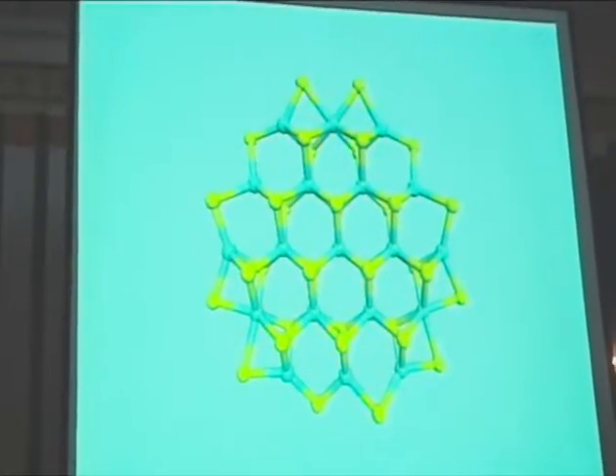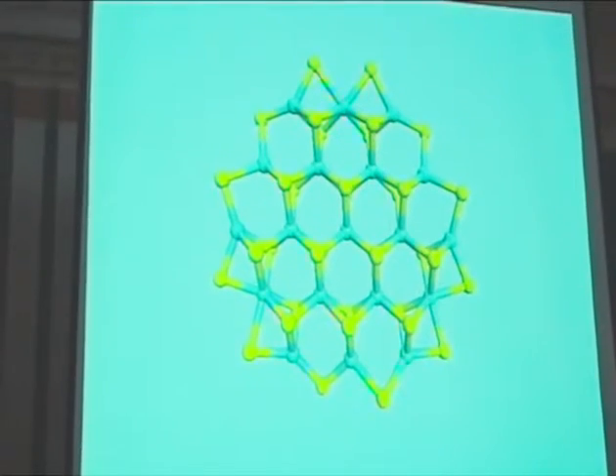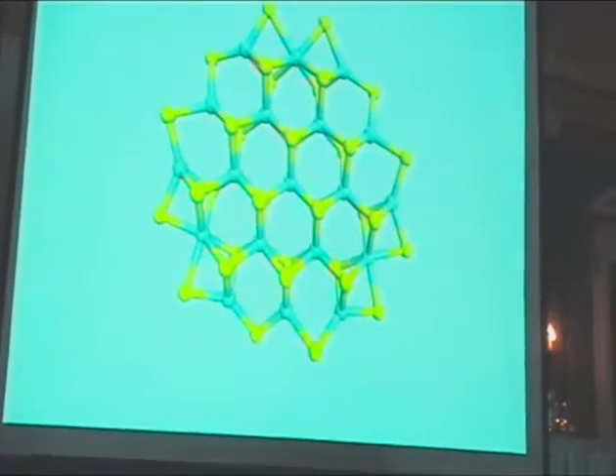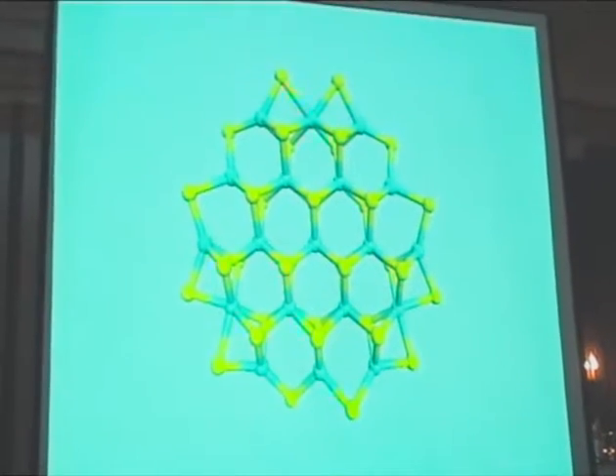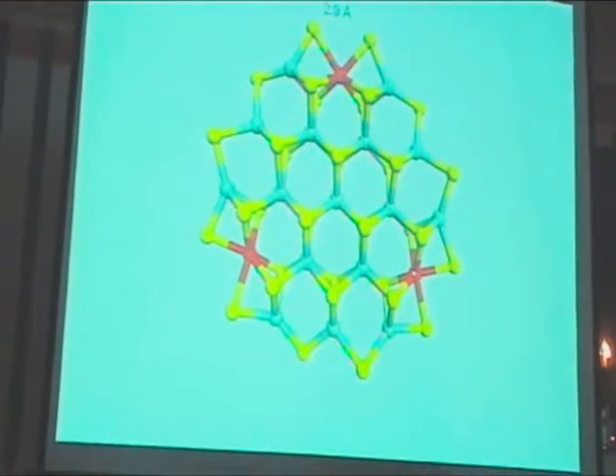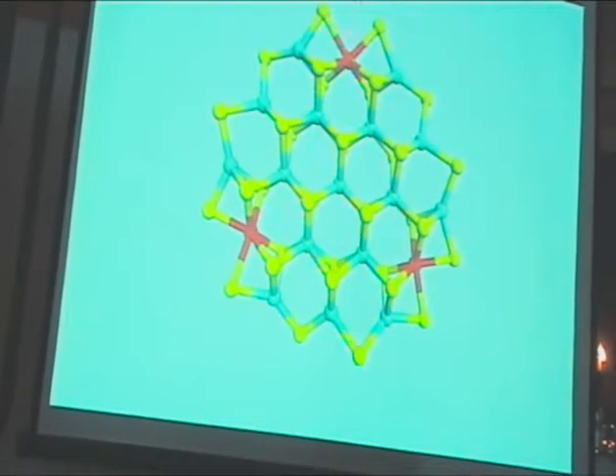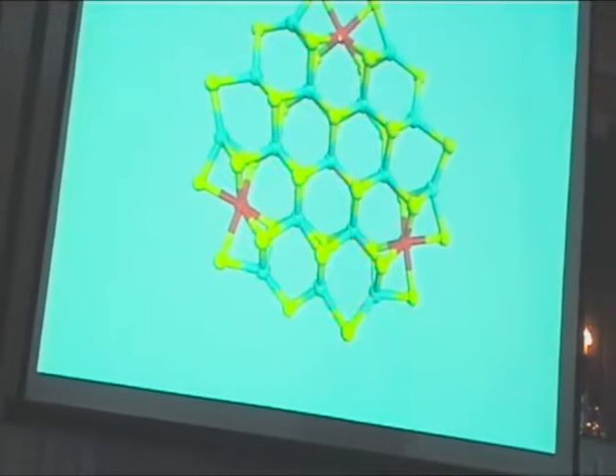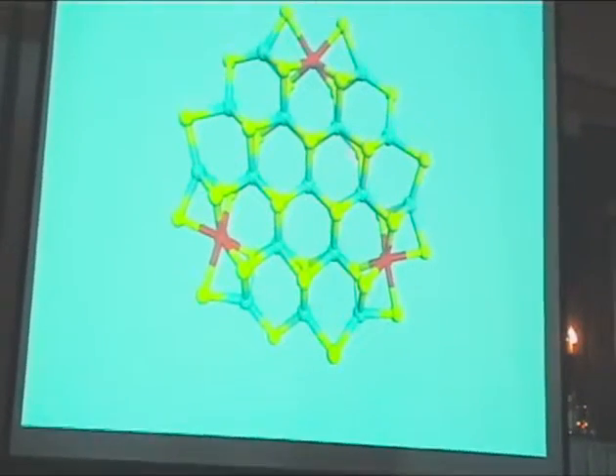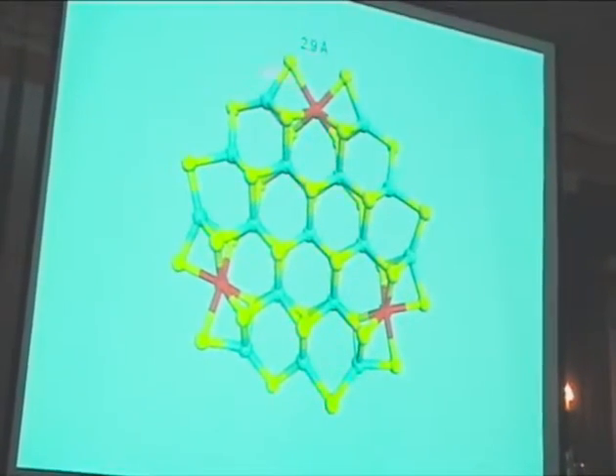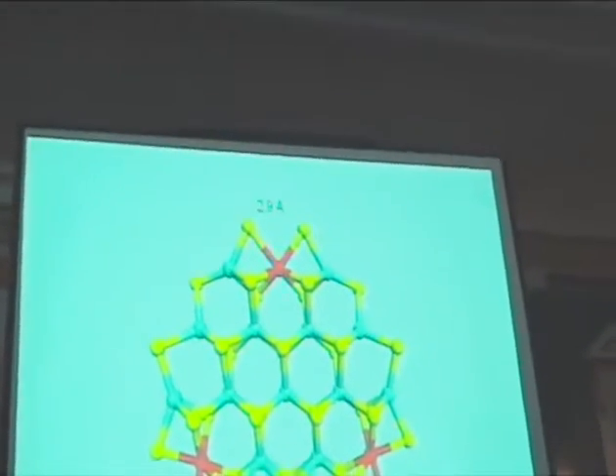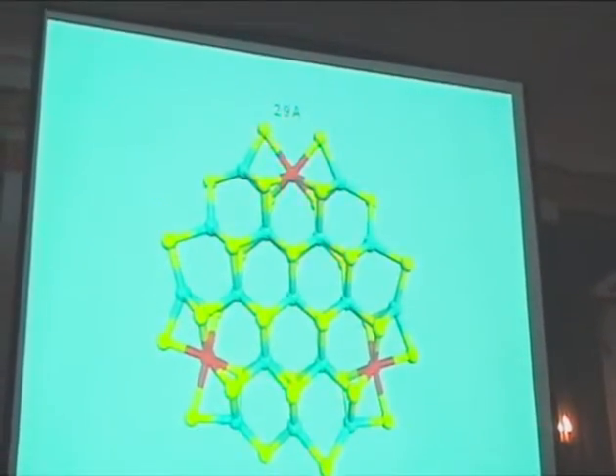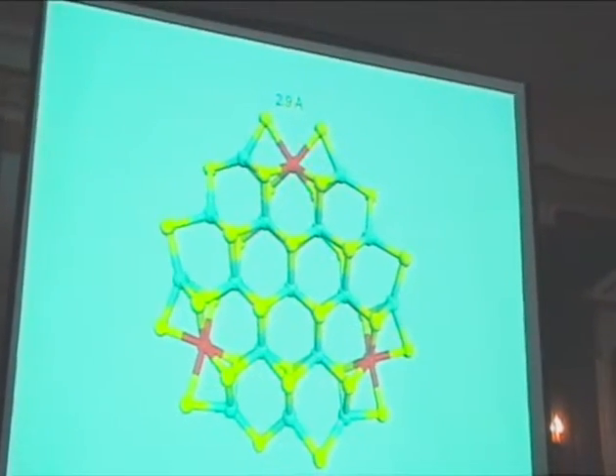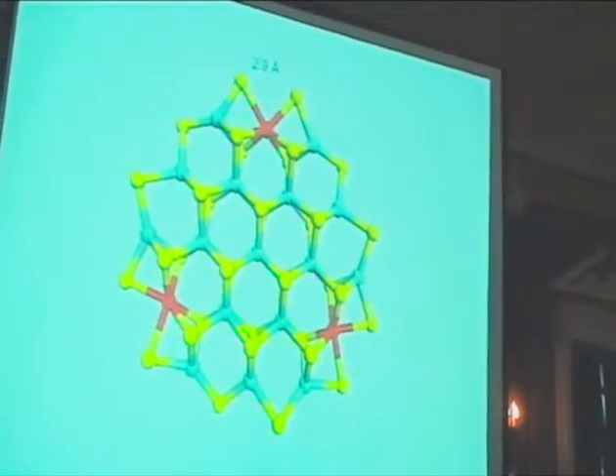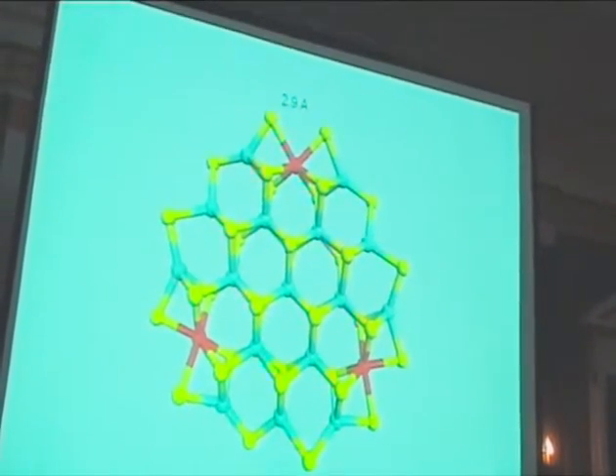We have done recently some DFT calculations, and indeed this shows a small particle, smaller than the one that is really there, but nevertheless it shows it, because now you can see that especially these molybdenum atoms have a shorter distance to the other molybdenum. And this distance is from the red one to the blue one, whereas all the other blues in the middle are the 3.16. So you see that indeed the DFT is predicting that you get a shortening, and it can be substantial. So it is to be expected, and indeed if you do the full analysis, but it's a complicated analysis, and you cannot do such a thing for any system, then you can get it out.